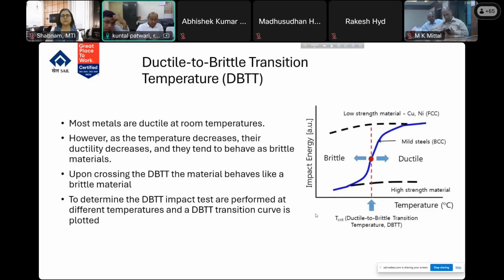Then this is the ductile to brittle temperature graph. The blue line which I am showing is the change in impact energy as we decrease temperature. The area to the left is the brittle area, to the right is the ductile area. Ideally, we should use our material on the ductile side. So we find out the serviceability temperature beyond which, if the material is used, it is prone to failure. That is the DBTT. It is essential for applications where the pipeline or the structure is facing very cold and harsh temperatures, wherein the material might also enter the brittle region. So in API specifically, we have this ITP and MPS. We are going to make the DBTT curve. We are going to test the sample at -80 as well, -60, -40, and this curve will be plotted.